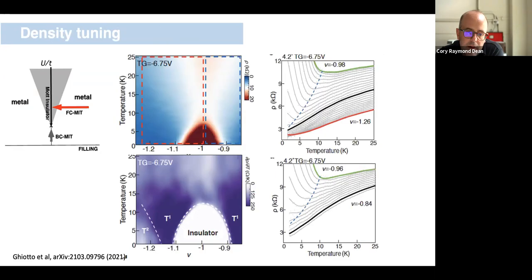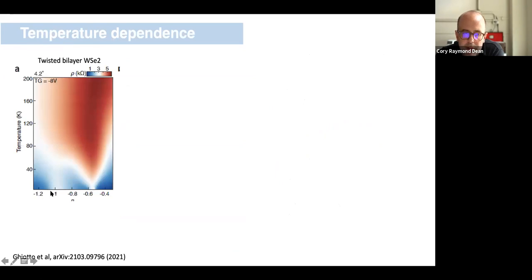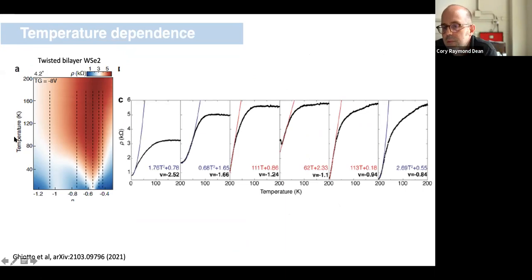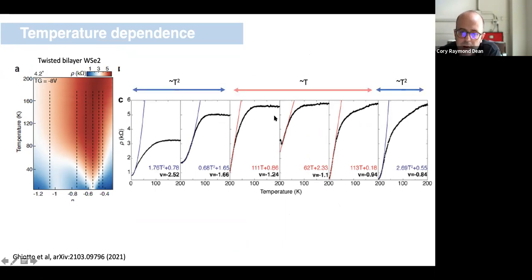So here again, I'm showing over a fairly narrow range of temperature and filling. So here, if we go to a much broader range of filling, so spanning now a broader range of density, and a much broader range of temperature, then what we can look at is how this evolves over those boundaries. So again, the critical point I'm trying to emphasize is that there is a region of doping far away from the half band insulator where we very clearly see something that looks like a parabolic dependence. There's a region where we see something that looks more convincingly like a T-linear dependence. And then at low doping, there's a region where we recover this T-squared dependence.